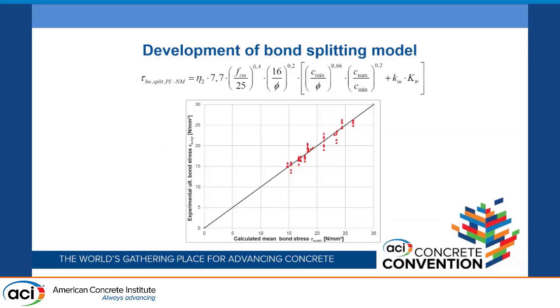And eventually, we came up with an equation very similar to what is given in the FIB Model Code. We found the parameters, so the coefficients or the exponents for concrete strength, rebar diameter, concrete cover, and so on. And then eventually, we came up with the pre-factor that would give us the best fit. And we can see that in all the cases, we got a very good match between this equation, the calculated, and the tested values.